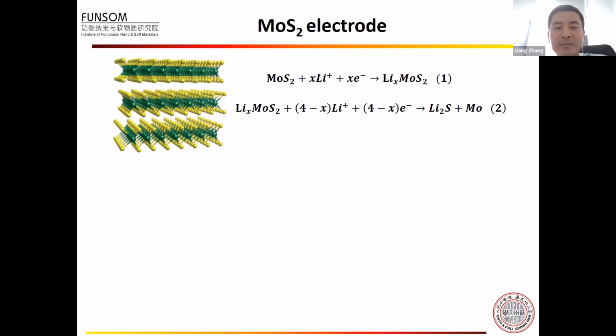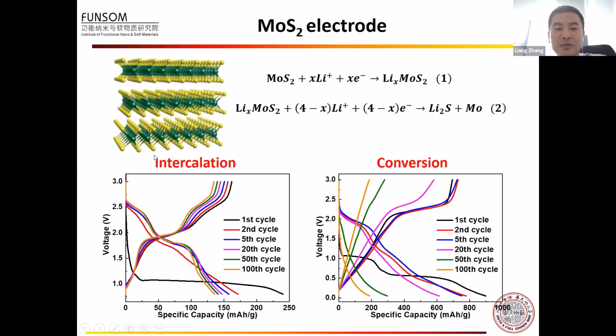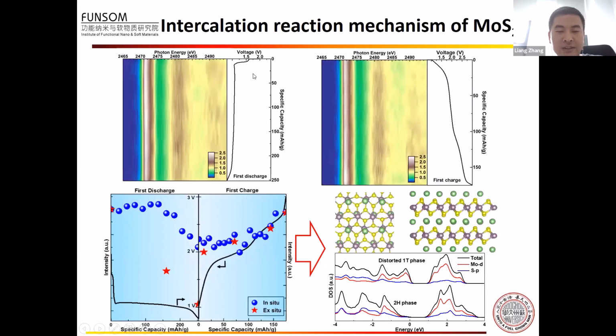During the lithiation process, it mainly has two reactions. The first is intercalation reaction. The second is conversion reaction. The intercalation reaction is very reversible. For the conversion reaction, with the lithium sulfide and the moly metal as the final product, the reversibility is still not very clear. Therefore, we use the sulfur K-edge XAS to investigate the reaction mechanism of the moly sulfide.